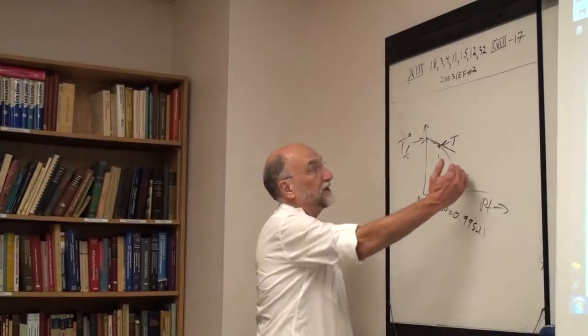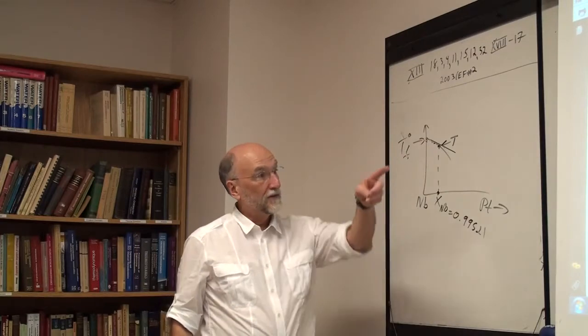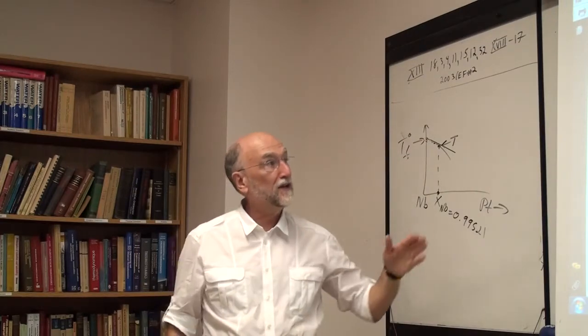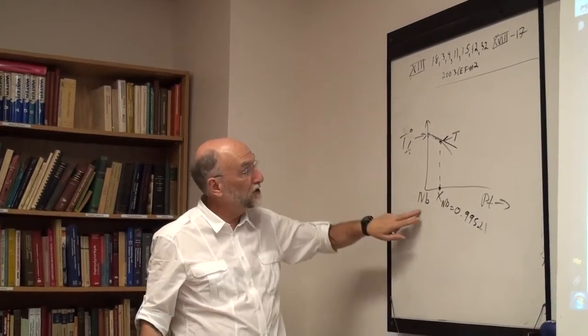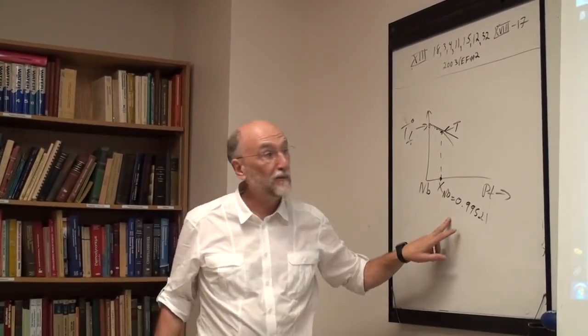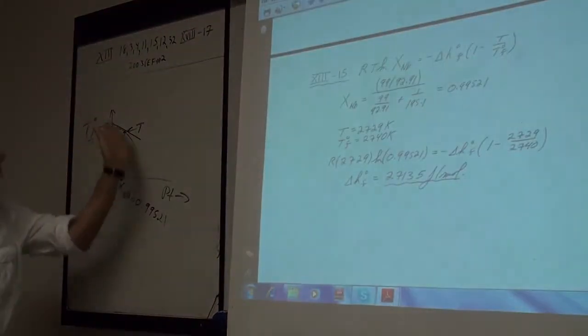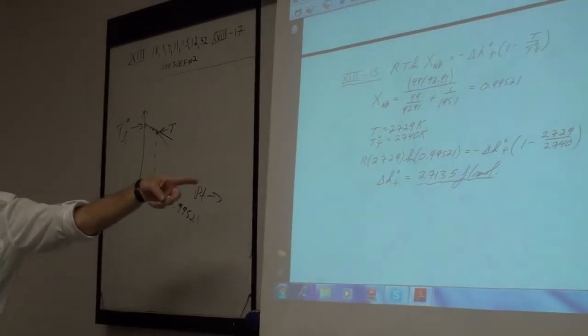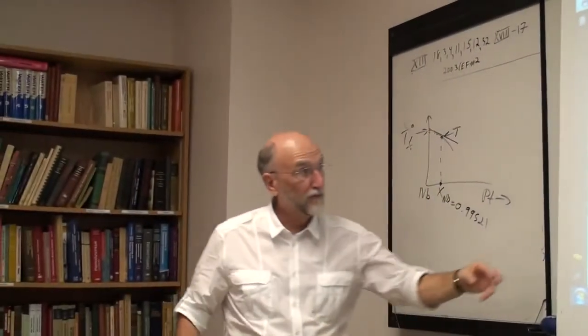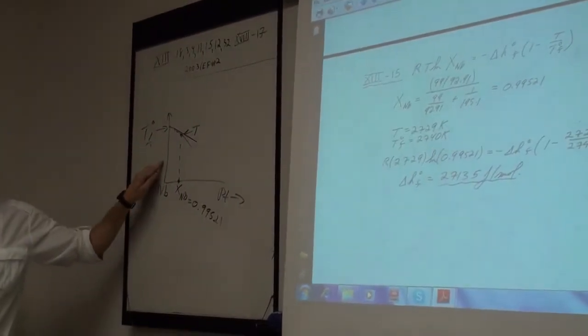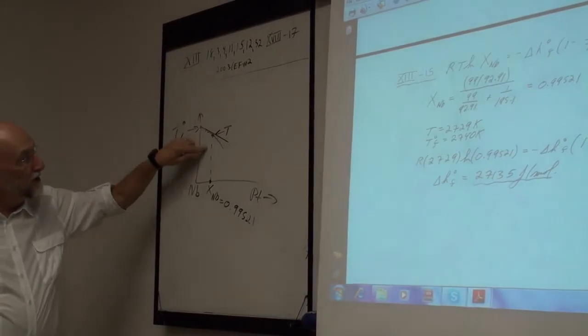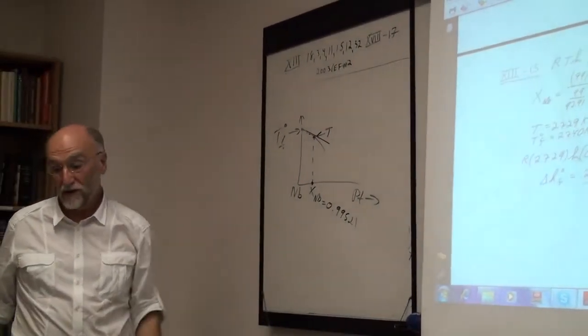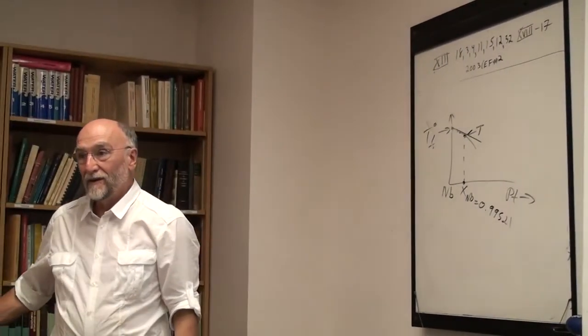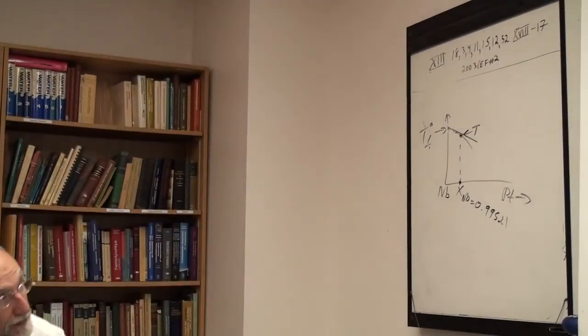And also, this is a check. Let's say you have a material now in which you do know the heat of fusion, at lower temperature, from calorimetric measurements. Then you can use this equation to check for solid solubility. If the limiting slope agrees with that equation from the measured heat of fusion, then you know that you have no solid solubility. If the limiting slope is a bit higher, then that would indicate you have some solid solubility. If the limiting slope is lower, it indicates that some of the thermodynamic data has got to be wrong. Okay. So checking your limiting slope is always a good thing to do.